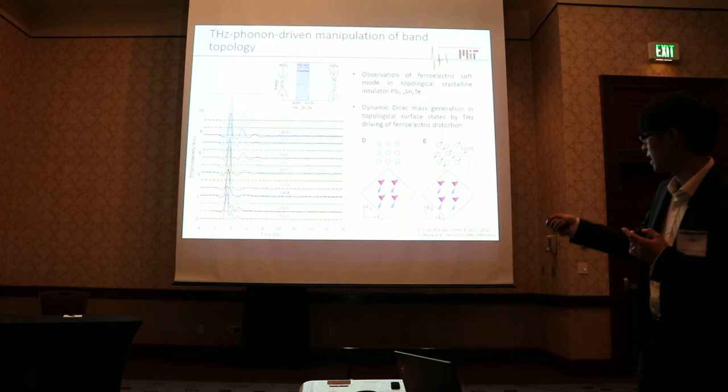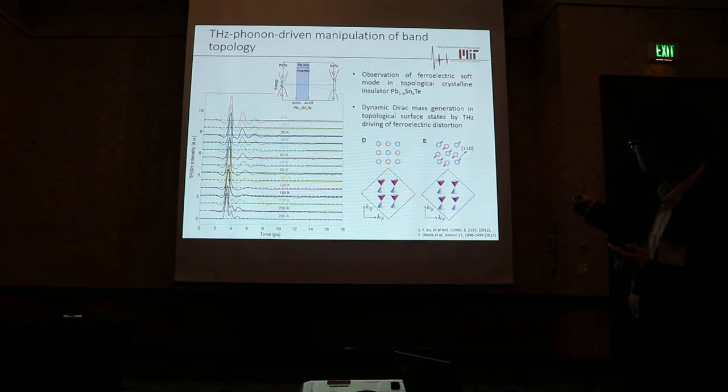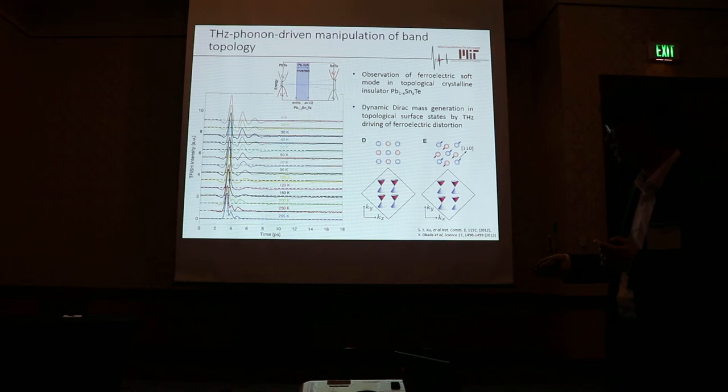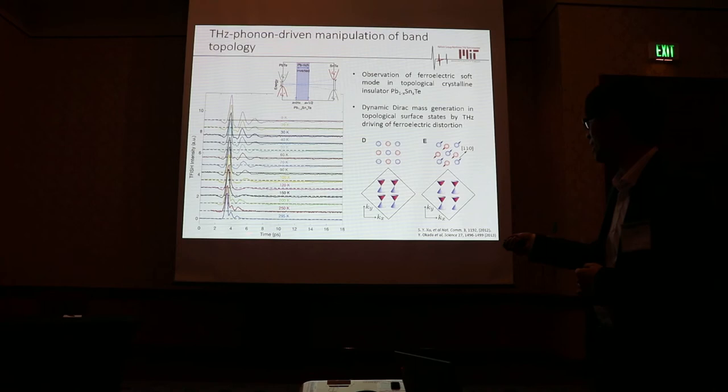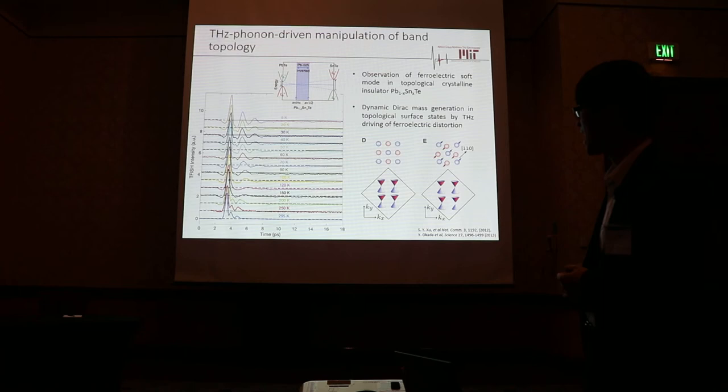Here's a THz experiment on lead tin telluride alloy at composition 0.5-0.5. We clearly observe a signature of the ferroelectric soft mode, as well as a ferroelectric phase transition. You can see that the phonon peak is getting wider and wider until it hardens again, which is clear proof that there is a ferroelectric phase transition in this material.